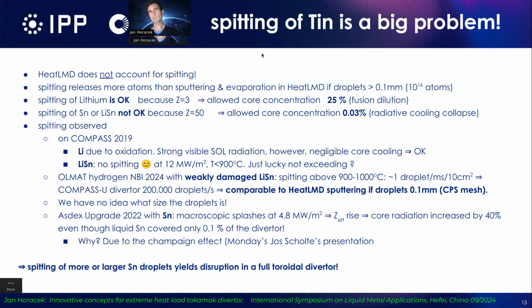What I still wanted to say is that the problem of spitting and splashing of tin is a big problem for tokamaks, because the heat LMD codes do not account for spitting or splashing, but it releases much more atoms than sputtering and evaporation. I calculated it would be more than this if the droplets are larger than 0.1 millimeter, because they contain 10^16 atoms.